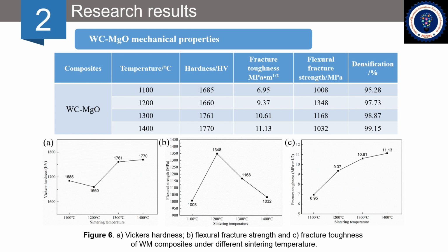As described in Figure 6c, the fracture toughness of WM composites increased with the increasing sintering temperature. Remarkably, the fracture toughness of WM composites did not decrease with increasing Vickers hardness, which is inconsistent with the fracture toughness of conventional binderless tungsten carbide composites and cemented carbide. An important reason for the fracture toughness increasing was that high fracture toughness corresponds to high density. Higher relative density will lead to fewer pores and better interfacial bonding.